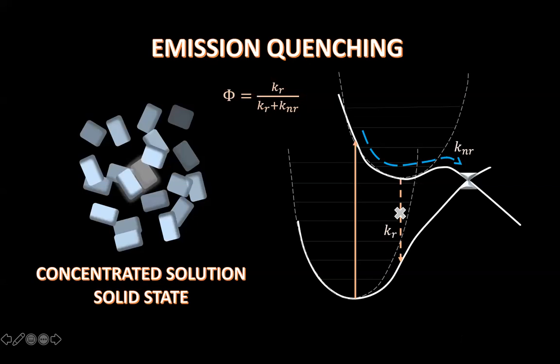The reason for emission quenching is that there are a lot of processes that occur at the non-radiative level that are related either to the overlap between the nuclear vibrational wave functions, or to the existence of conical intersections that happen in regions of very strong coupling between the vibrations and the electronic wave functions. So emission quenching will happen when you find charge transfer states that generate these conical intersections, or when you have very strong interaction between the vibrational wave functions.